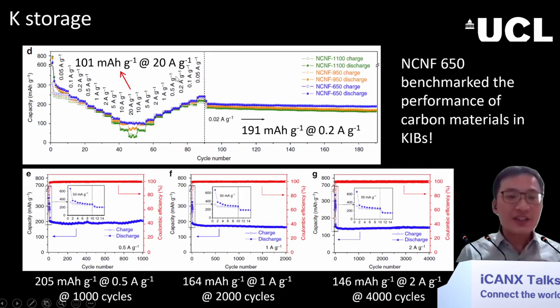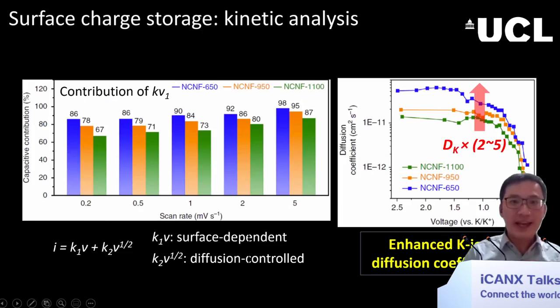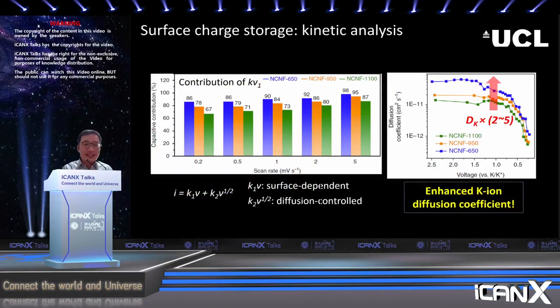We try to understand why the 650 degrees material can have such a good performance. What we did is we used different electrochemical techniques to characterize where the charge is stored in the material. Is it on the surface of the material, or is it inside the bulk of the material? So the results showed that for the 650 degrees carbon material, it has the highest contribution of the surface potassium storage. And we also tested the potassium ion diffusion coefficient in the bulk structure of the material. And results showed that the 650 degrees material has the highest diffusion coefficient among the three samples.